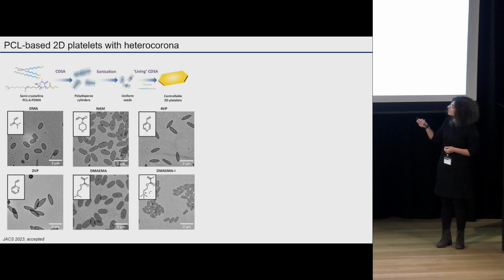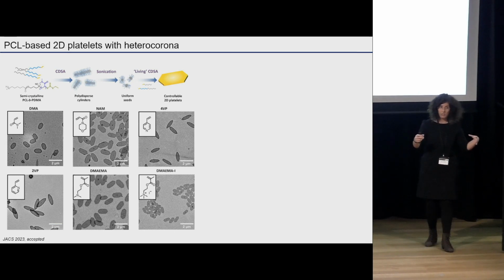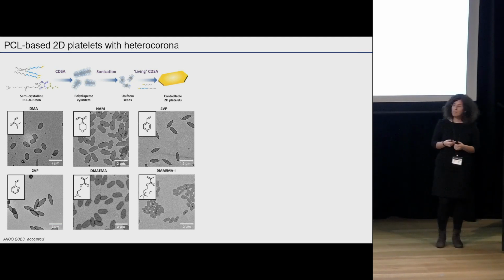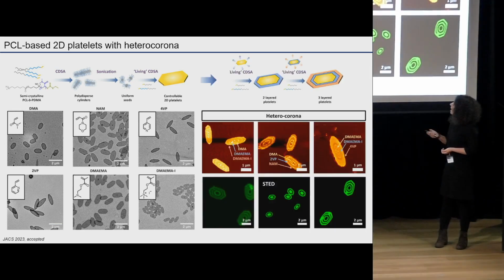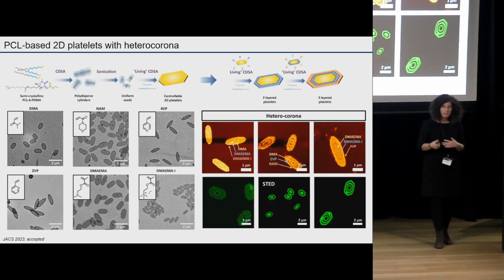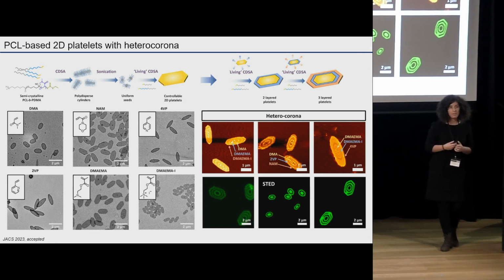For example, in here, when you use an aromatic ring with a heteroatom inside, as you can see in this picture here and this picture here, you can get more elongated structures compared to a more hexagonal structure when you use non-aromatic species. And the other thing you can do is mix all these polymers together. Because of the ability that we have to add polymer to the nanoparticle, we can not just control the size in this way, but we can also control the surface chemistry composition.